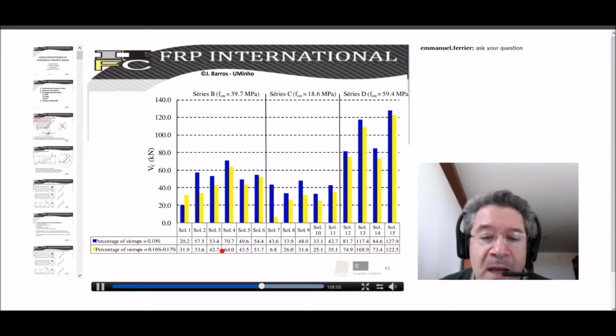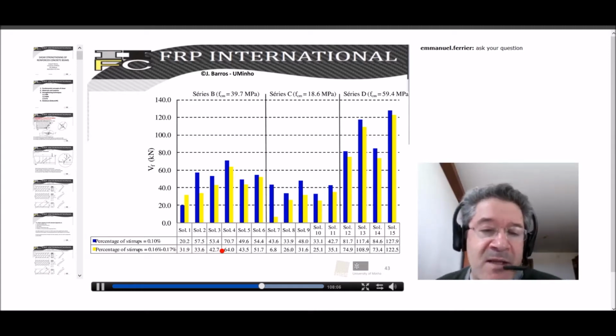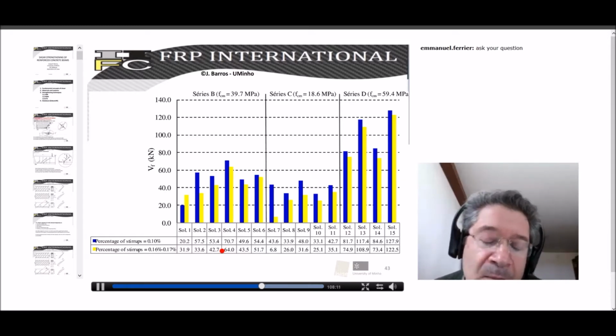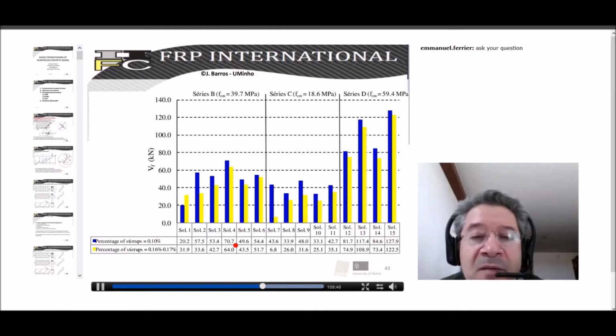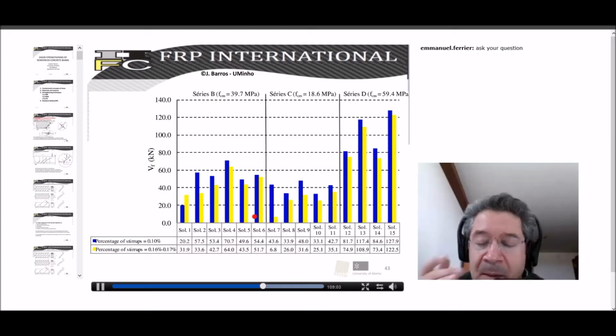Another very important conclusion that we obtained from this series of tests is about the effect of the percentage of existing steel stirrups. In yellow, we have the contribution of the CFRP beams when using the highest percentage of steel stirrups, between 0.16 and 0.17. In blue, the percentage was 0.10. From these graphs, it is clear that, in general, the higher the percentage of the existing steel stirrups, the lower the effectiveness of the shear strengthening arrangements.